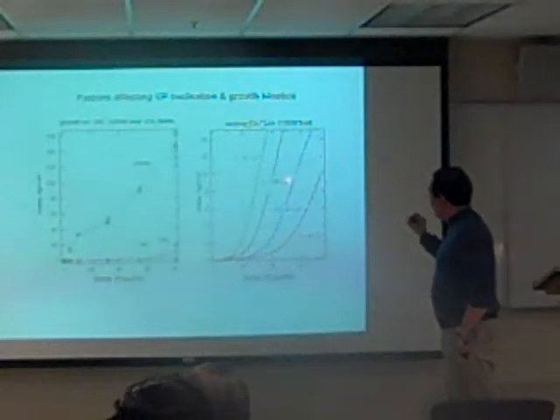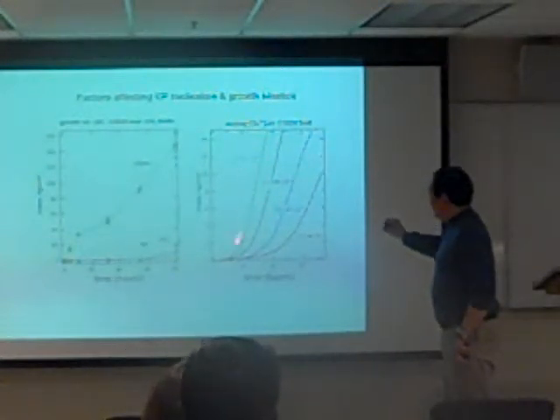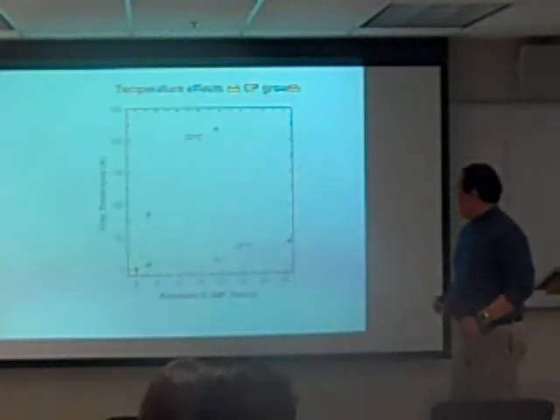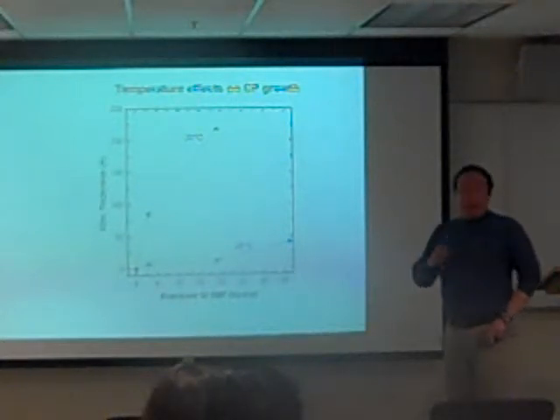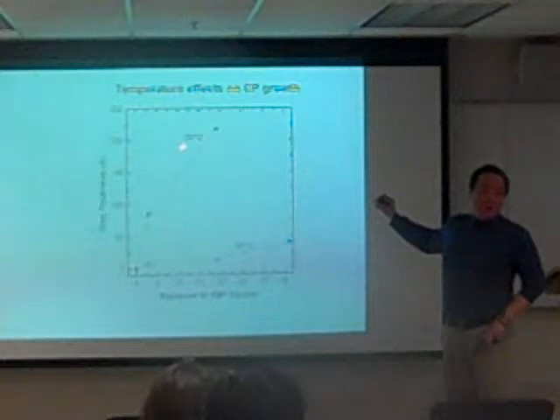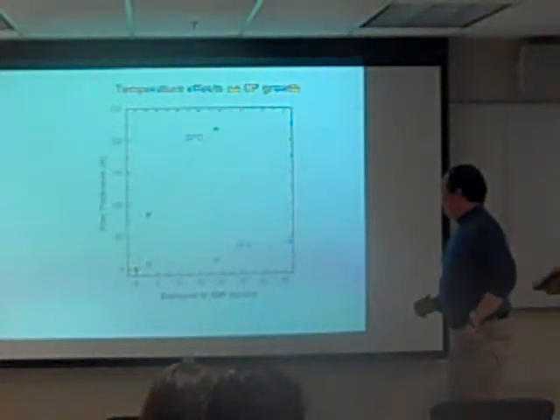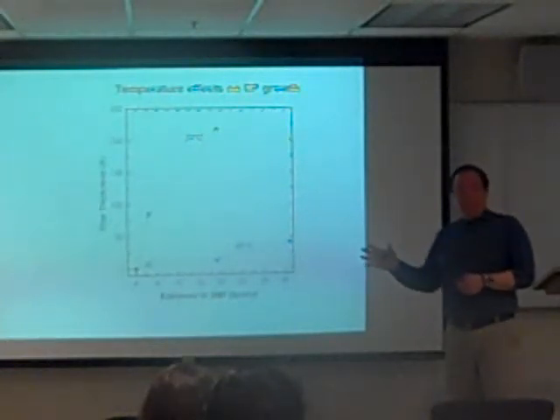Another thing that affects the rate of growth is the concentration of the calcium. Okay, so if you vary the calcium here, you can see a greater concentration of calcium results in faster growth. Temperature also affects this. So this is growth on the carboxylic acid functionalized SAMs. This is at room temperature. You see slow growth, and then at physiological temperature, it grows faster. So in terms of trying to form the crystallites, we use the physiological conditions at pH 7.4 and also this physiological temperature as well.